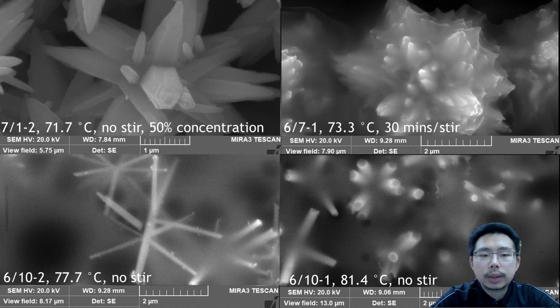One thing we noticed was as the temperature increased, each rod of the zinc oxide nanostructure were getting more defined. As you can see on the top two, their temperature were both around 70 degrees Celsius, and it looks more like a nanoflower structure. And for the bottom two, the temperature goes around 80 degrees Celsius, and they look more like a rod structure.